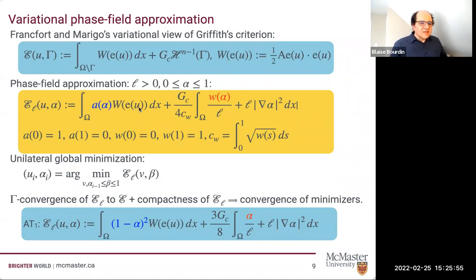So here you see that u is now a smooth function. There's no jump of u, so the integrals are in omega, not in omega minus gamma. But u is a function in H1. Alpha is a function in H1. But what you can show is that this E_L converges to the Francfort and Marigo energy in the sense of gamma convergence. And that implies that the minimizer of this converges to the minimizer of Francfort and Marigo. So this free discontinuity problem, which is a tricky problem involving minimizing with respect to a function and an unknown curve, is simply replaced by a standard problem of minimizing a functional that depends on two smooth functions.